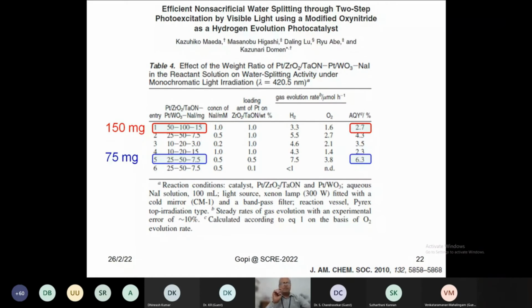But the message I want to give is that when the photocatalyst amount is 75 milligram, they are getting an efficiency of 6.3% apparent quantum yield, or simply efficiency. When they increase the amount of catalyst from 75 to 150 milligram, you can see that the efficiency has come down by more than 50%. Can you imagine that increasing from 75 milligram to 150 milligram of powder material brings the efficiency down by more than 50%? How can we scale up to 1 gram, then 10 gram, 100 gram or kilogram? This is clearly not going to work out.